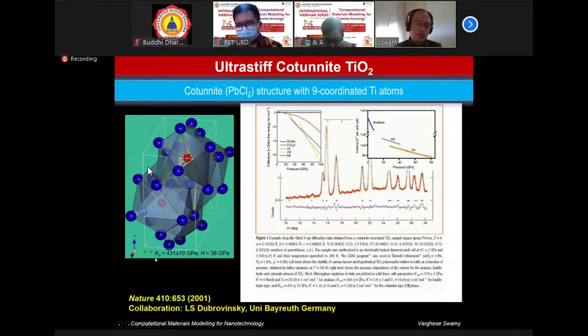And that gives a huge bulk modulus, which means you can't compress this material. It is highly incompressible. And at that time, we measured a hardness of something like 38, which is very high. Actually, subsequently, we found it was slightly less than that. That's not important. So we have produced what may be considered the most incompressible oxide phase of TiO2 at that time. That's why it got published in a good journal.